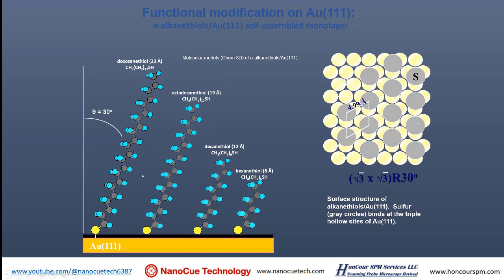And when this happens, more and more molecules attach to the surface, and they actually form a two-dimensional packed crystal. These molecules stand up and form a crystal. And so the old surface of gold will be replaced by these molecules, and therefore any contaminations, pollutions will be replaced. That's very good. That's very awesome.